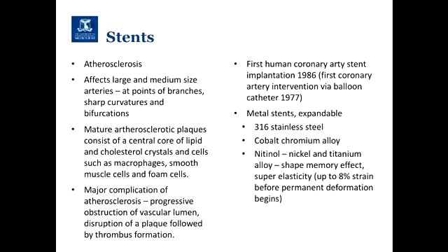Nitinol has a shape memory effect. So if you want something that opens, well, not opens and closes, but you expand and you decrease, do you want it to have a shape memory effect? It is very elastic, particularly for a metal. That's not usually a property that you associate with a metal. So for this type of alloy, you can strain it up to 8% before you get permanent deformation.